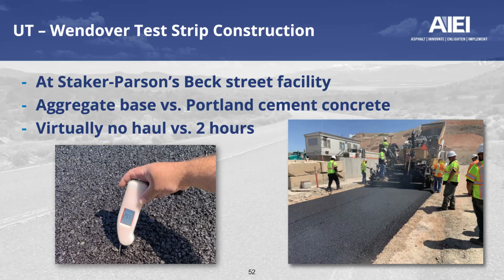They have some other notable differences. Not only is this not produced and being laid on concrete, and being laid on an aggregate base, but unlike Wendover, there is no haul. Mix production temperatures are rated about 300 degrees Fahrenheit. And so moving from the hot plant, which is just a little bit out of the site of the picture on the right, to the site is virtually no haul whatsoever.